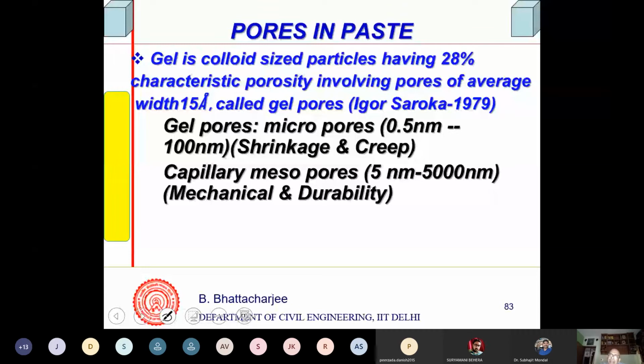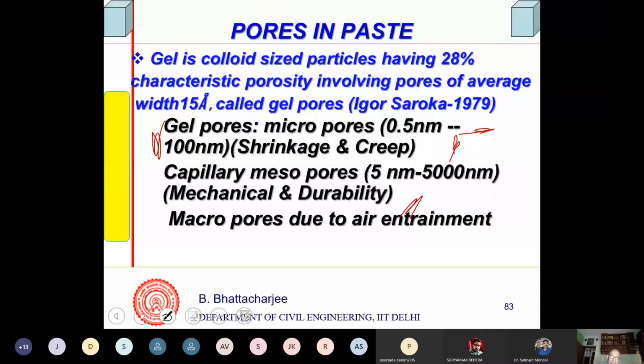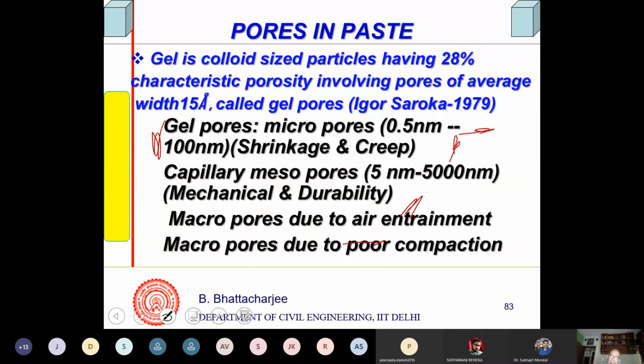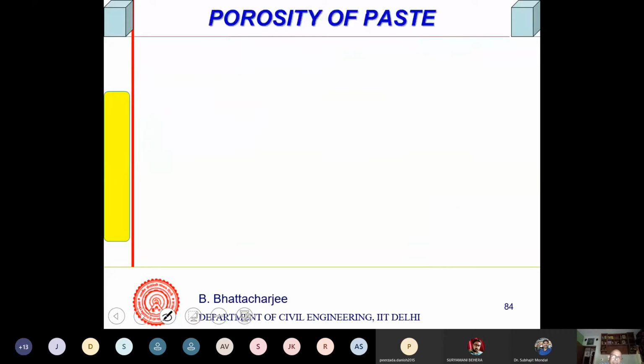Right? So this is a book, Igor Soroka. You get all this information there. And these gel pores, fine pores, are responsible for shrinkage and creep. Capillary pores actually reduce the strength and are also related to durability. And there are larger pores because of air entrainment. And if you have poor compaction, additional pores will be there. So you have pores in the system inherently.